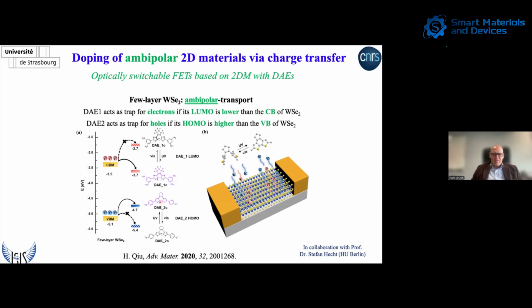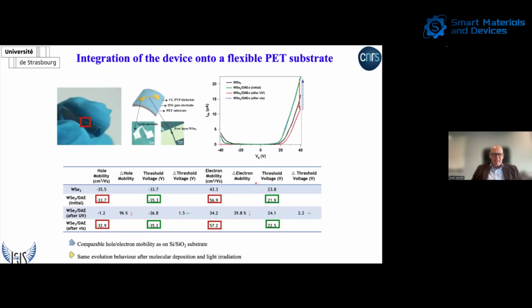And so the idea is pretty simple: we physisorb a blend of these two molecules on the basal plane of the tungsten diselenide in our device. Doing that, we can start from a hole mobility of 35 and an electron mobility of 43. Upon physisorption of the molecules in the open state, we have more or less the same hole mobility and a slightly increased electron mobility, which is quite remarkable. Then, upon UV light illumination, we observe a decrease of 96% of the hole mobility, going down to 1.2 centimeters squared per volt per second, and a decrease of 40% of the electron mobility, which is totally recovered upon visible light illumination.